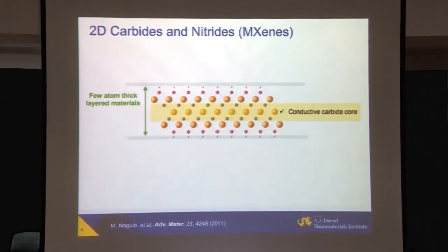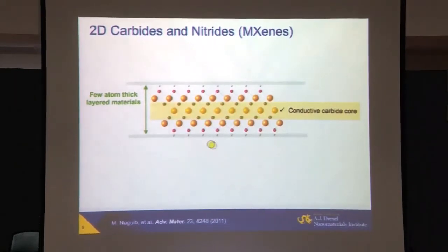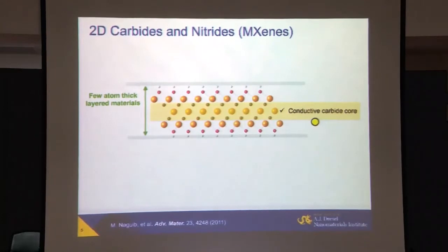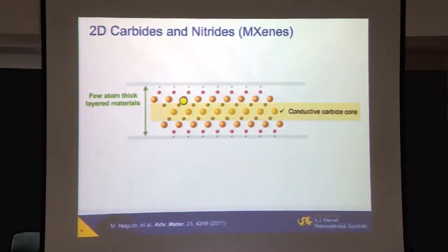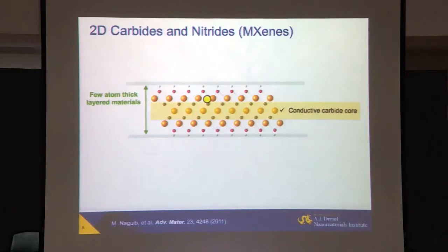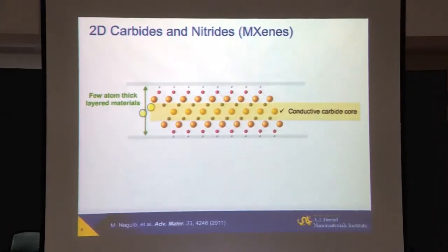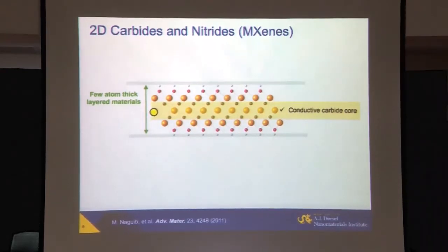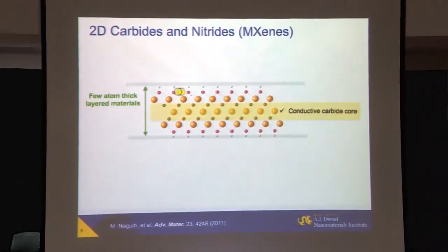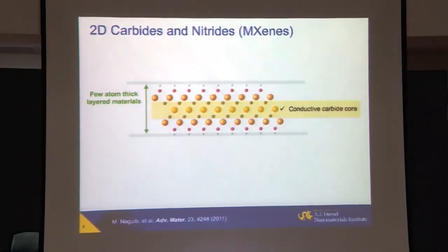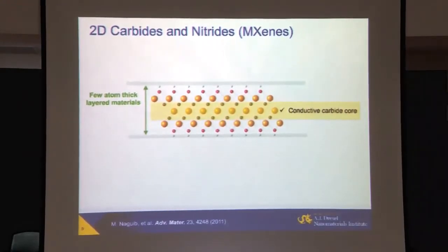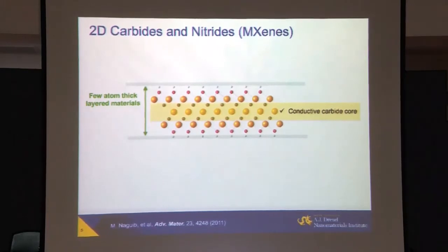One of them: most of them, not all, but most of them, in terminated state, are metals. They have conducting carbide cores. And these large golden spheres are transition metal atoms I'm showing to you. The small dots in the middle, the black ones, are carbon and nitrogen. And I'm showing the surface termination by OH groups because we produce them by wet chemical synthesis here. So they are conducting inside, but on the surface they look like clay or graphene oxide.